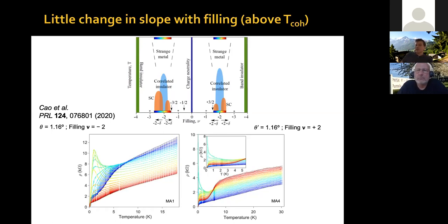Now, that gives you a rough estimate, plus minus 0.1 degrees or something like that. Then we can do measurements in a magnetic field and look at the Landau fan diagrams, which give us Shubnikov-de Haas oscillations, which go very sharply to a given point. Because we know that that's, let's say, 2 electrons per moiré unit cell, we can determine very accurately where that point is. So we know the area more accurately, and we know what the twist angle is more accurately. On a high quality transport device, that can give us plus minus 0.02 degrees or so. If we do scanning measurements, we can determine this locally and with much higher precision, actually.